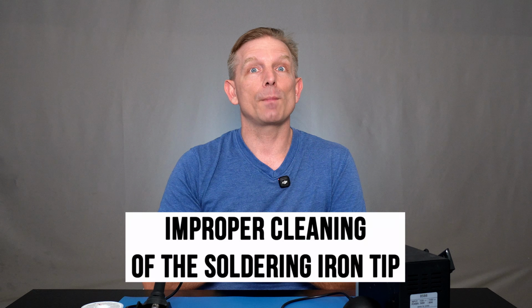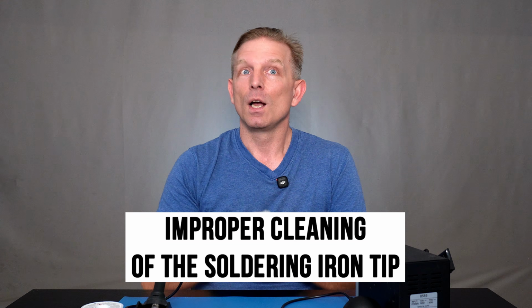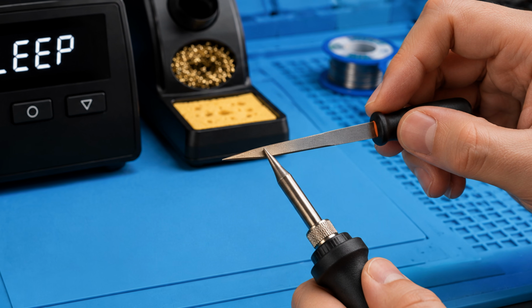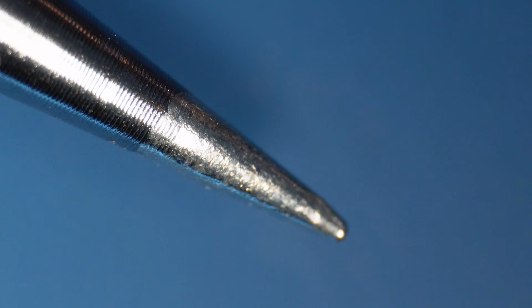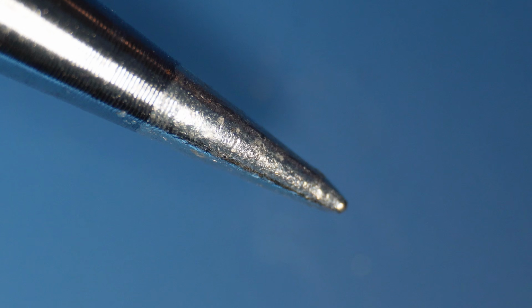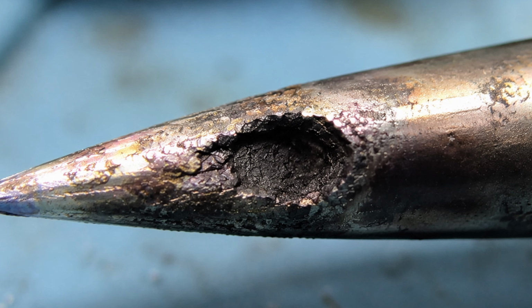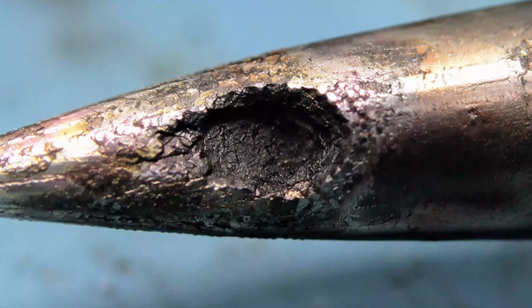Reason 3. Improper cleaning of the soldering iron tip. When the solder stops sticking, many take sandpaper or a needle file. On modern interchangeable tips, this cannot be done. You remove not only dirt but also scrape off the protective iron coating. As soon as the copper core is exposed, the molten solder begins to gradually dissolve the copper and pits are formed. After that, you need a new tip.